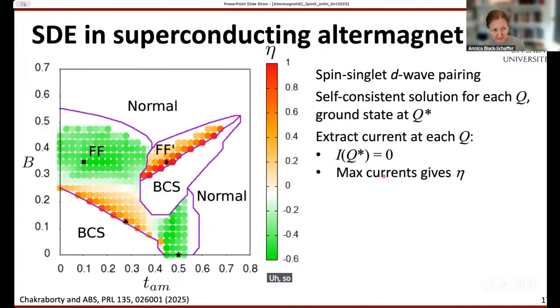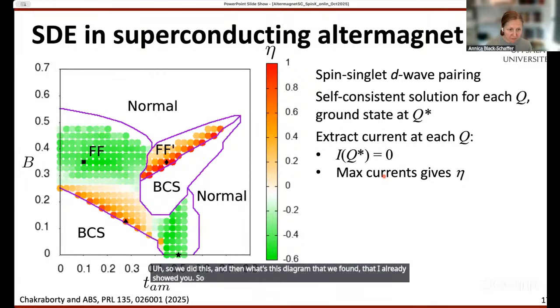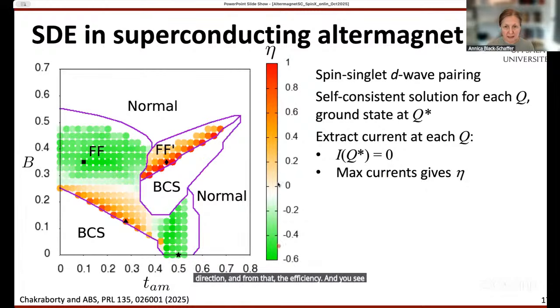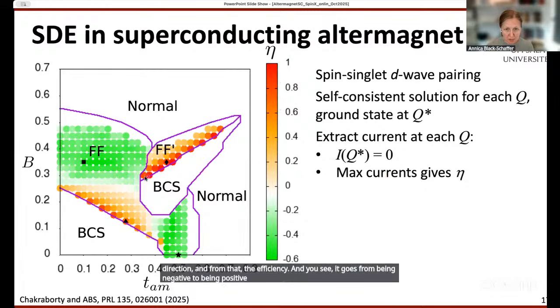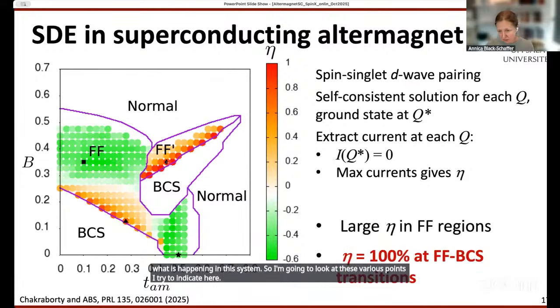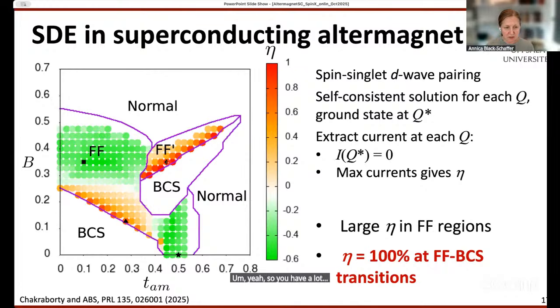So we did this, and then we found this diagram that I already showed you. Here, for every little blob, we calculated the currents and extracted the maximum currents in both directions, and from that the efficiency. And you see it goes from being negative to being positive, and most notably it actually reaches 1 along this line and for some points here. I'd like to try to explain to you what is happening in the system, so I'm going to look at these various points I tried to indicate here. So you have a large efficiency, and it's even 100%.